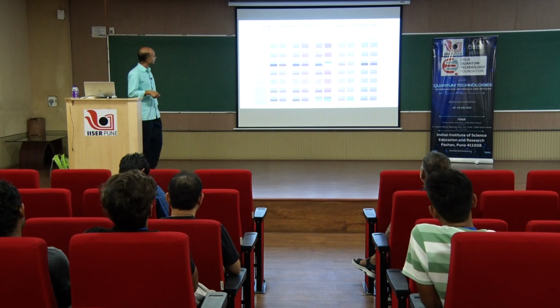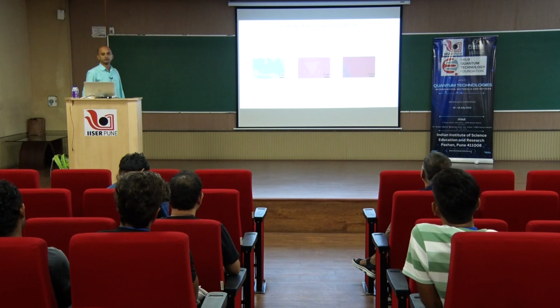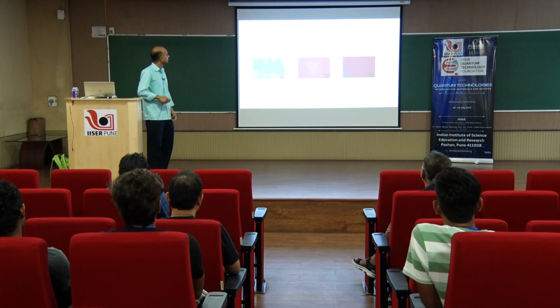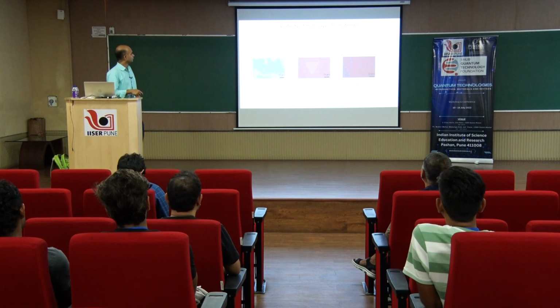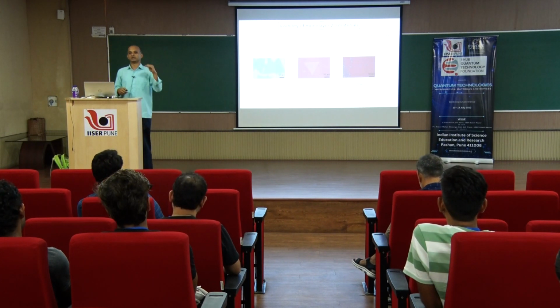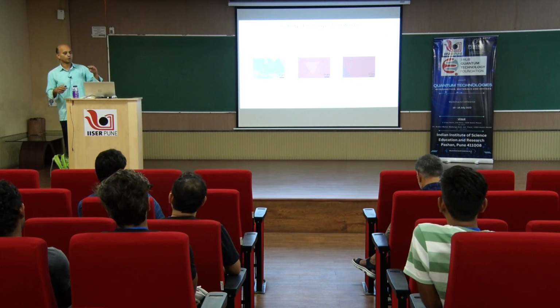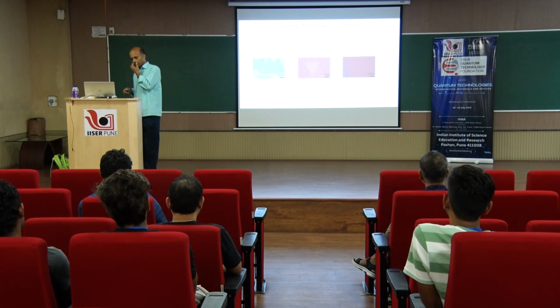So, here is a list of the most commonly used materials and the thickness that you should be using. And what we do in our lab is we mostly use SiO2 on top of silicon coated substrate. The thickness is around 280 to 300 nanometer, which gives us the sweet spot. There is another sweet spot that is close to 80 to 90 nanometer of SiO2. The reason that device people do not use that is that thin SiO2 is highly prone to pinholes, so it can leak. So, we generally require a little bit thicker SiO2. If you are doing optical studies, then 80, 90 nanometer is perfectly fine, you can use that.